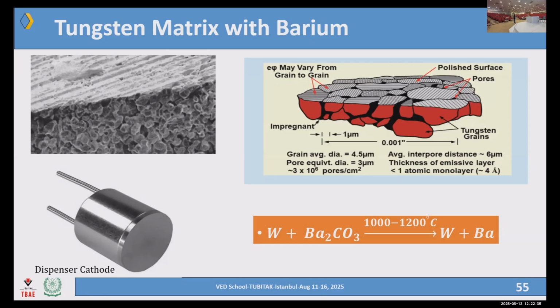This is the cross section of the porous tungsten. You see the machining, it's already very rough. It's already very rough. It is our life. I mean, it's made of powder. It's made of powder, then it's sintered, then it's machined. But again, this is not the real world. Again, this is a cartoon on our right hand side. These black parts are basically this barium carbonate. They seep when heated. They slip through these openings, not openings, pores, and then they are deposited on this side. This is like buttering your bread.